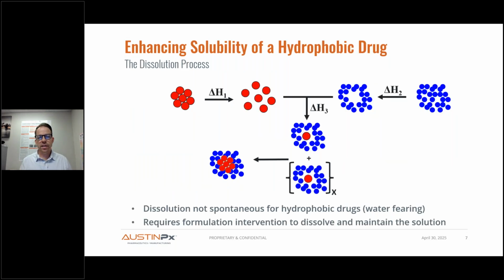So how do we enhance solubility of a hydrophobic drug? We'll look at this conceptually through the dissolution process and understanding that for hydrophobic drugs, the dissolution process is not spontaneous, right? You've got this stable crystal lattice, you've got to dissociate the molecules from each other. That requires a certain amount of energy. Then there's this cavitation within the aqueous solvent that you need to create, which requires energy. And then there's the energy of hydration to hydrate these individual molecules.